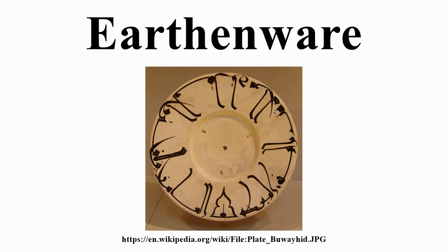Terracotta is a term used for sculpture and utilitarian objects such as plant pots, tiles, and drainage pipes made of earthenware. Characteristics: generally, earthenware bodies exhibit higher plasticity than most whiteware bodies and so are easier to shape by ram press, roller head or potter's wheel than bone china or porcelain. Due to its porosity, earthenware, with a water absorption of 5 to 8%, must be glazed to be watertight. Earthenware has lower mechanical strength than bone china, porcelain or stoneware, and consequently articles are commonly made in thicker cross-section, although they are still more easily chipped.